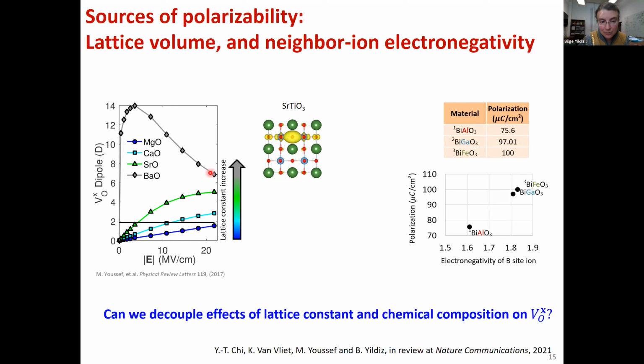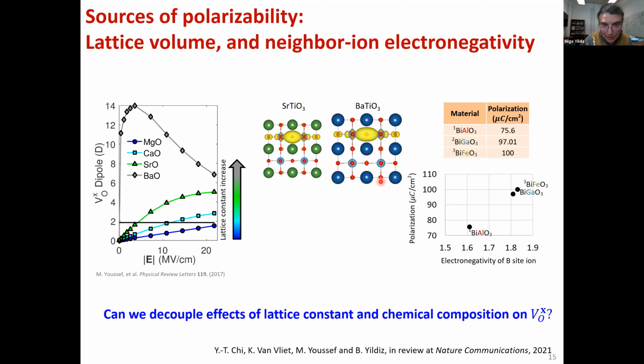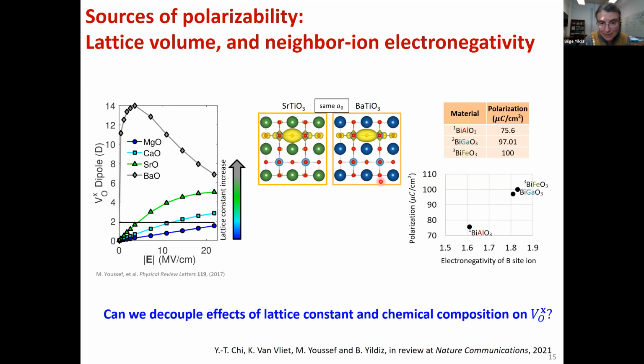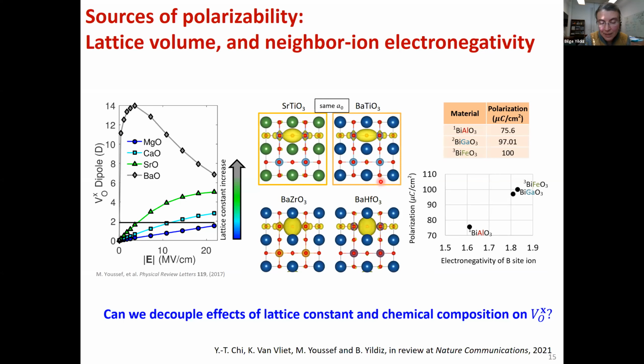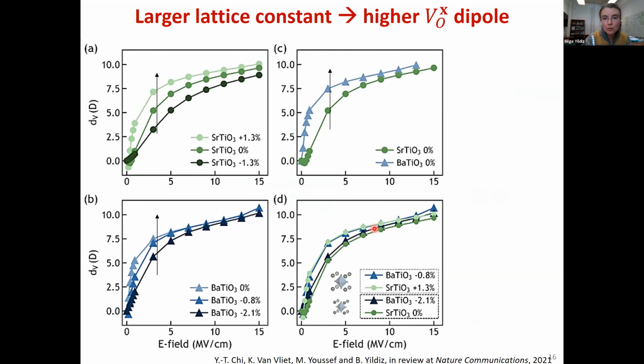Okay, so one way that we can resolve this lattice constant or lattice volume effect is by applying strain in the strontium titanate system. And we can contrast strontium titanate to larger lattice parameter materials like barium titanate, which is a very high K dielectric material. And we can even artificially fix them to be at the same lattice parameter with very similar chemistry to see if we obtain the same polarizability. And we can contrast a class of oxide like titanates to zirconates and hafnates, which have distinctly different electronegativities compared to each other. Okay, so let's look at the strain effect first.